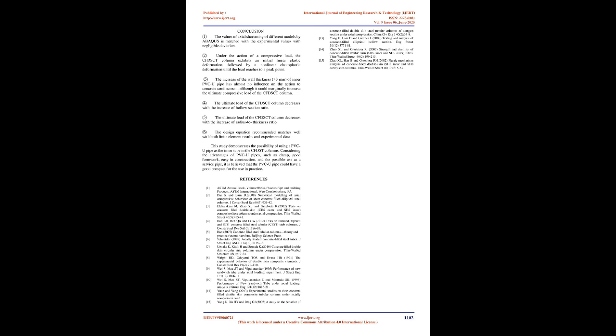As far as the confinement is concerned, it was found from the finite element analyses that the inner pipe has almost no influence on the circumferential strain of the outer steel tube when the wall thickness of the pipe is greater than 3 mm. Conclusion. 1. The values of axial shortening of different models by ABAQUS is matched with the experimental values with negligible deviation. 2. Under the action of a compressive load, the CFDSCT column exhibits an initial linear elastic deformation, followed by a nonlinear elastoplastic deformation until the load reaches a peak point.